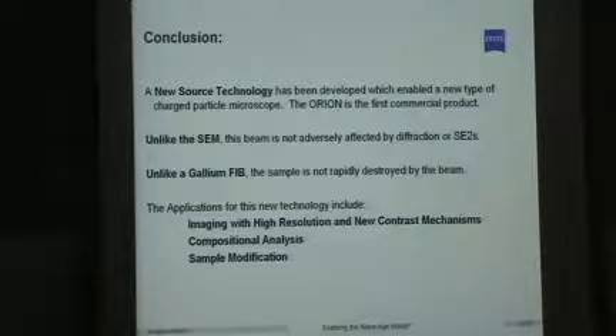So wrapping it up and leaving time for some questions, we developed this new source technology, which allows us to make this new type of microscope, the gas field ion microscope. I expect in the future there will be others trying to enter the market with these microscopes. Right now it's only a Zeiss product. Unlike a SEM, this beam is not adversely affected by diffraction or SE2s, so we can get sharper images for both of those reasons, sharper than a traditional SEM. Unlike a gallium FIB, the sample is not rapidly destroyed by the beam. That's where the damage starts to come into play.